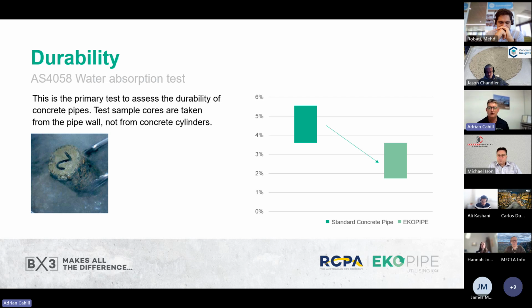So the requirement for the Australian standard is a maximum of 6%. Our typical values for concrete pipe range 4 to 5%. Our experience with eco-pipe has been a fairly significant reduction, and we run in the vicinity of half, so in the sort of 2 to 4% range for water absorption. So that provides a lot of confidence when it comes to the durability.